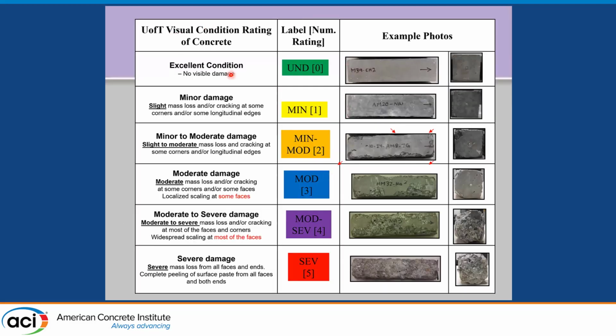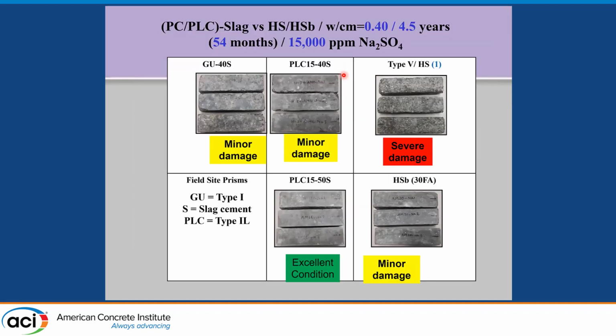I'll just show you 3 slides here. We used a visual rating system. Mike had a different numerical rating system for his concrete than Ashlee did. We sort of used the stoplight approach: green is good, red is bad, and other colors are in between. We looked at these concretes on an annual basis. They were in either magnesium sulfate or sodium sulfate, 15,000 ppm, underground in temperatures that range from 3 degrees C to 15 degrees C year round, because they were stored underground, and we monitored their condition.